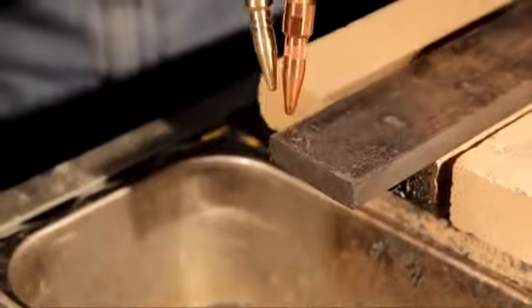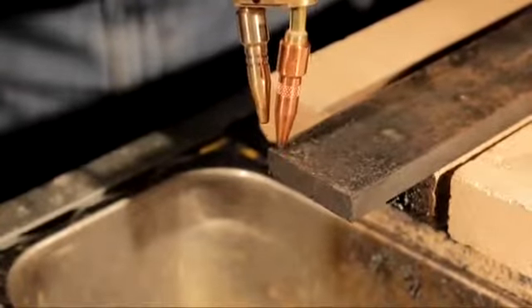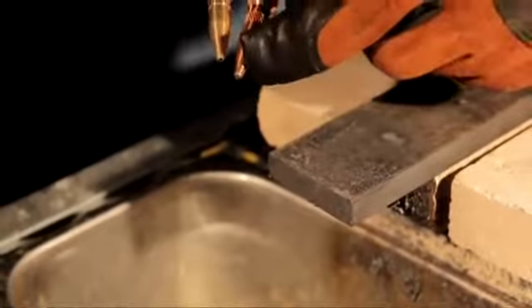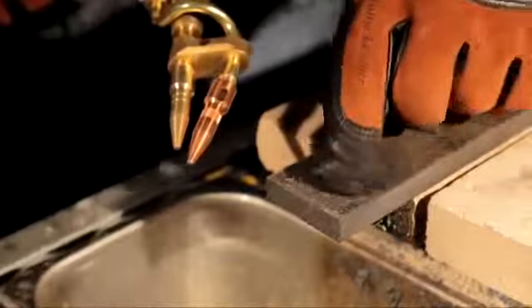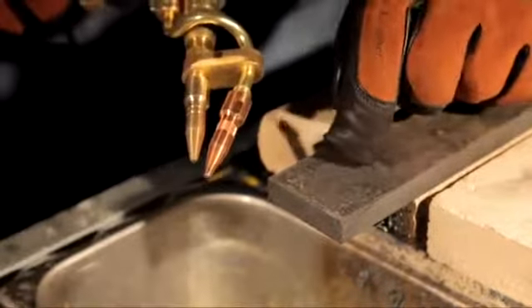Keep that copper tip where it's straight up and down, right down close to the metal. Remember, the closer to the metal on your cutting tip, the nicer, thinner, finer, cleaner cut you're going to get. On all thick metal, we have to preheat. Remember that.